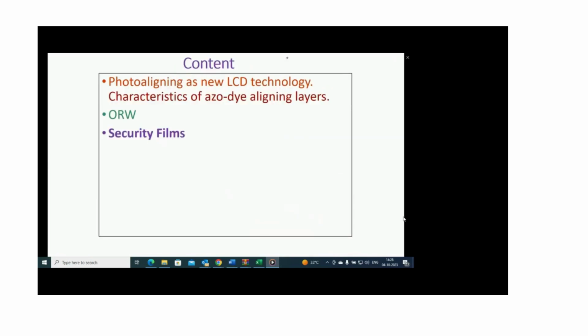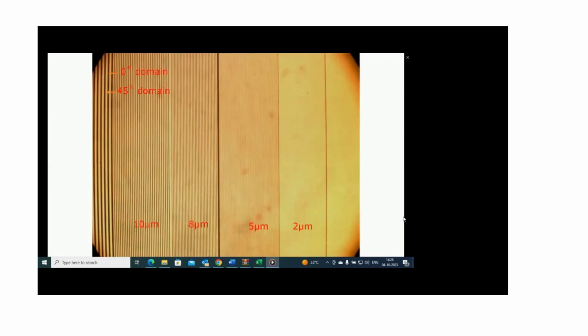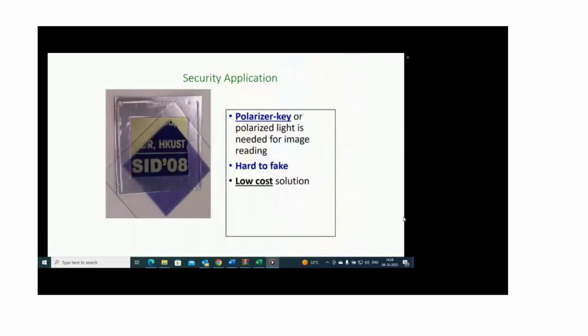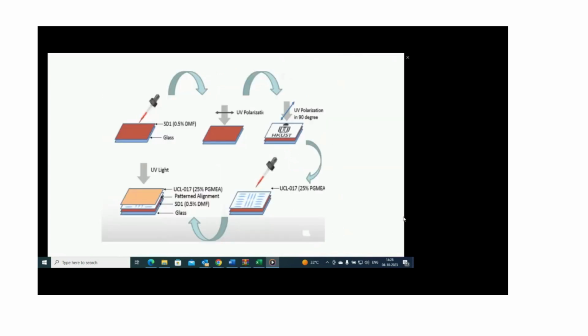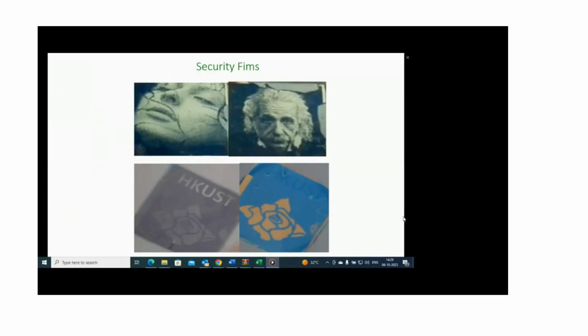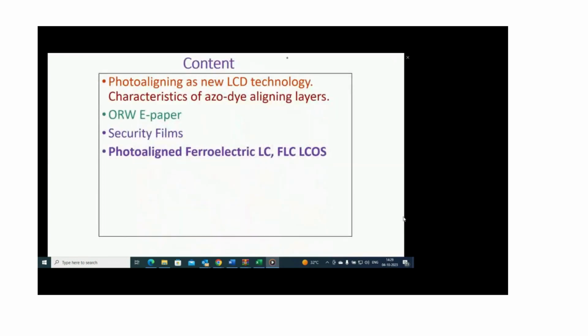Next, let's go to security films. For security films, because we have very high resolution, it is easy to make them, and the security films will not be seen without special polarizers. So what we are doing, we put azo dye with liquid crystal monomer, then make a picture, polymerize the liquid crystal monomer, and then we can have full color, black and white, high resolution, or even color images. An image can be changed if you rotate the polarizer. So this is a new type of security film.